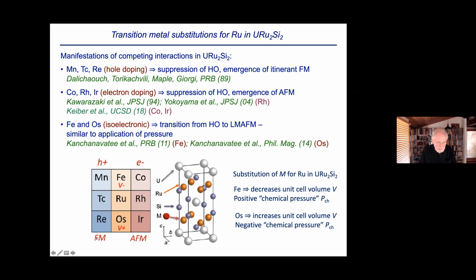And in this part, you find ferromagnetism in all these cases. This was done back in '89. And then in this case, there was a lot of work done on rhodium where you find antiferromagnetic behavior, and then some recent work we've done with cobalt and iridium also show that you get antiferromagnetic phases. Now, iron and osmium, which are isoelectronic, drive this material out of the hidden order phase into the large moment antiferromagnetic phase, and is very similar to the application of pressure. And this just shows where these substitutions are made.